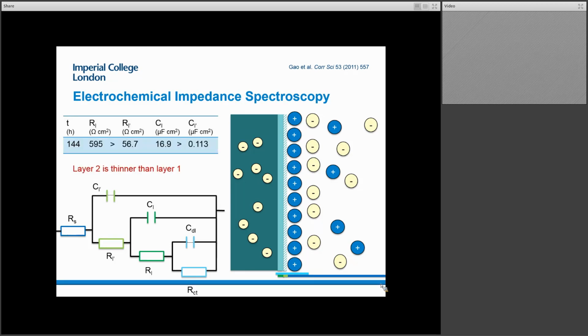Okay, so what more can you get out of this? And the answer is actually potentially quite a bit. It sort of depends on what else you know. But one of the things the authors point out is that the resistance of the layers is an order of magnitude apart. And in fact, the resistance is so demonstrably different that they hypothesized that the new layer must be thinner than the original layer, or rather than the layer which was originally there, which may have changed thickness. So this poses a very interesting point that you're starting to think about the evolution of the sample and the evolution of those layers.